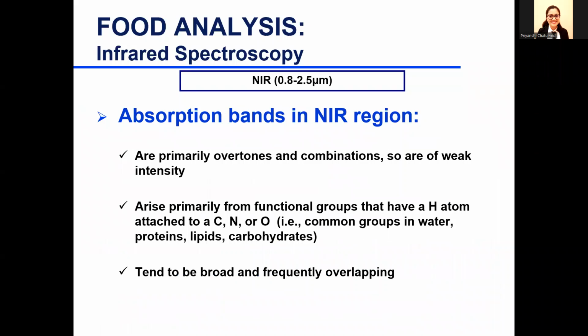I was talking a little bit about near IR. Let me just say one more thing about near IR. Near IR can check overtones. So another thing is, if you've got a lot of water in something and it's swamping out your signal, go up to the near IR frequency and you should be able to see things. So again, it takes more energy because the absorption intensity is not as high, but that's another way to avoid water swamping.